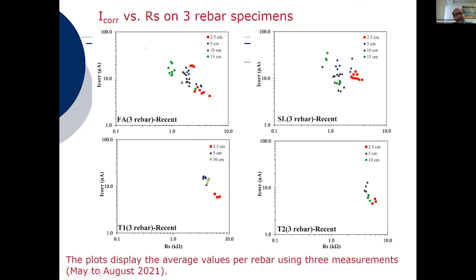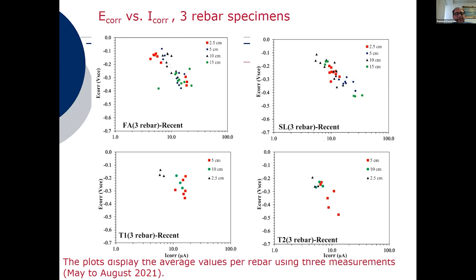And you can see that there are a couple of trends for the FA specimens, T1 and T2, but there is quite a bit of scatter for the samples that are SL. So that means that for a given solution resistance, there is a range of corrosion currents that were observed. And this is the data that was measured between May and August of this year. So let me move to the next slide.